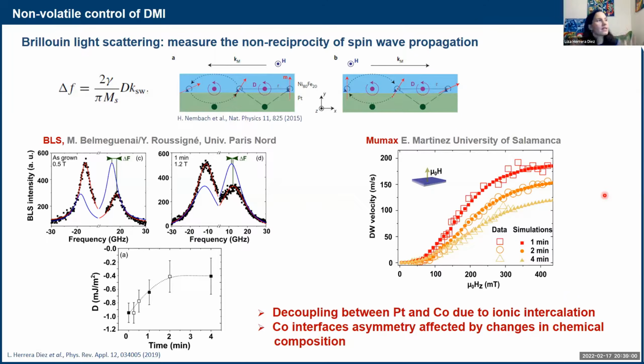As I mentioned at some point, our interpretation for this is that these ions that we know are going very far could be getting in between the cobalt and the platinum, inducing a decoupling between the two layers, and also making this interface a little bit more rough. And then this has a detrimental effect on the DMI that we can see here decreasing.